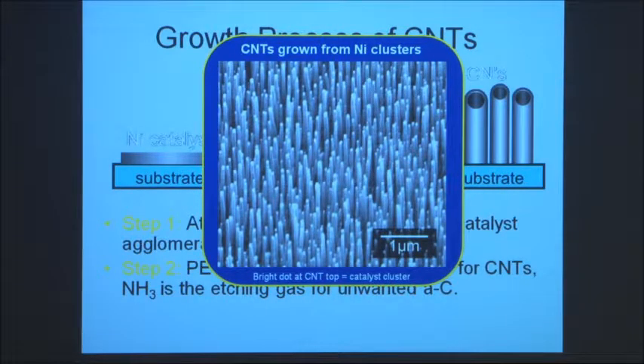So you can do this by putting them in a plasma-enhanced chemical vapor deposition system. Essentially, you have two parallel plates. You have a substrate in the bottom plate. You apply a plasma. And within that plasma, you get a sheath field produced, and the nanotubes line up in the direction of the sheath field. So here we go. Bunch of nanotubes lined up, but hopefully you can see that there's quite a variation in the height in these nanotubes, and if you look closely, you'll see the variation in the diameter as well. And that's purely because they start off from this different distribution of nickel balls in terms of diameter and size.